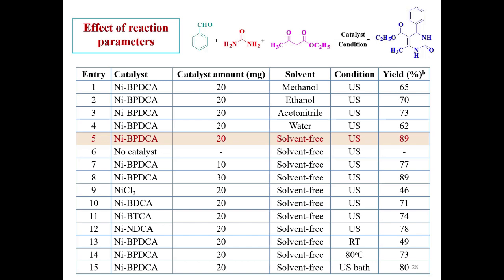Accordingly, we have conducted this reaction in the presence of the nickel metal organic framework with BPDCA as the organic linker. We use the catalyst amount of 20 milligram constant, and only change the solvent: methanol, ethanol, acetonitrile, water, and under solvent-free condition. Another condition we have used is the ultrasound cavitation technique. We observe that in the case of nickel BPDCA, under solvent-free condition in the presence of the ultrasound cavitation technique, 89% yield is obtained, whereas in the presence of the different solvents, methanol, ethanol, acetonitrile, water, the percentage yield is very low, less than 75%.